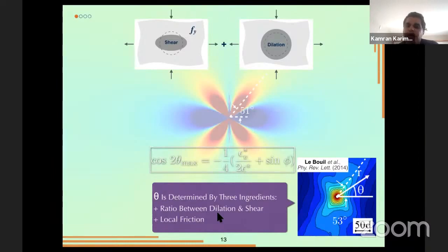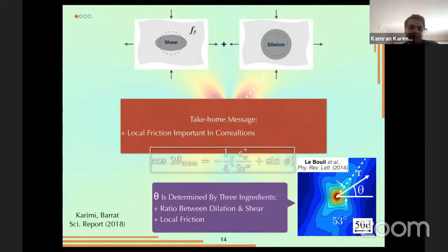Everything is based on linear isotropic homogeneous elasticity. So that's a big assumption. And maybe we can play with these 2 local or material-based parameters and give a better match with the experimental results. So the take-home message is that local friction and dilation are important in terms of the dynamics of these precursors that occur prior to the failure. So let's move on to the second part of my talk.